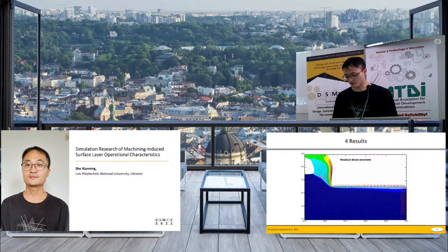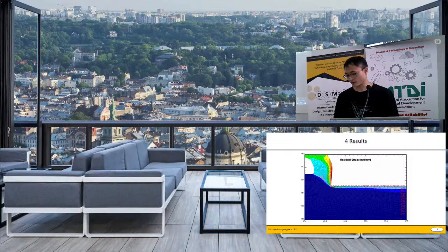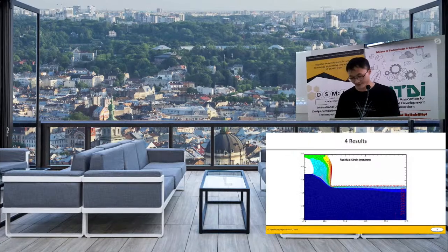The micro hardness of the material surface layer is responsible after its operation at high operating temperatures. A sign of burnout of alloying elements may be a change in the parameter of the crystal lattice of the heat-resistant alloys. With increasing degree and depth of hardening of heat-resistant alloy, their fatigue stress when working in an environment with high temperature decreases significantly. Next slide, please.